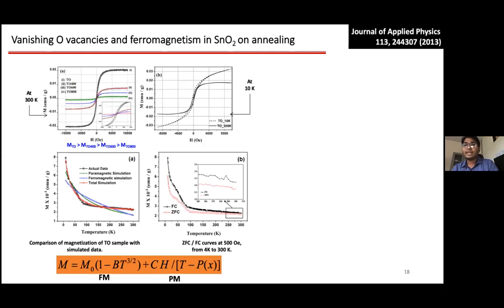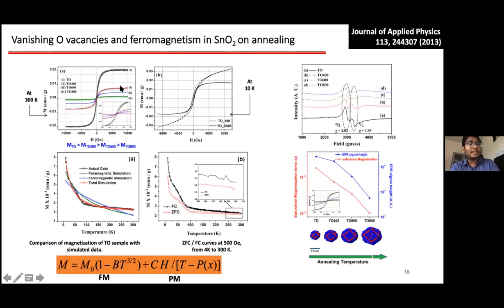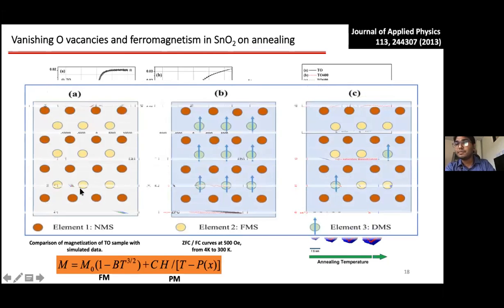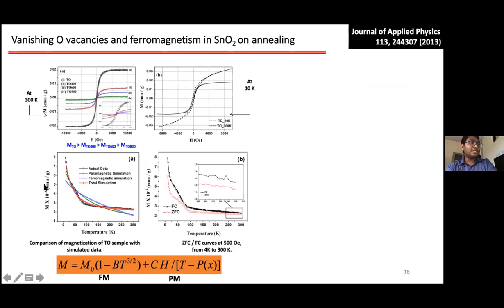So then we did more magnetic measurements on the annealed sample. As you can see, in the annealed sample, the saturation magnetization went on decreasing, and even the hysteresis kind of disappeared. And then we did some temperature dependent measurements and simulated those with a combination of ferromagnetism and paramagnetism. Basically, you can see that at low temperature, it shows more of a 1 by T type of variation, which is Curie behavior. So it's somewhat paramagnetic at low temperature, and at higher temperature it still has this flat component, which can possibly point at some ferromagnetic interaction.